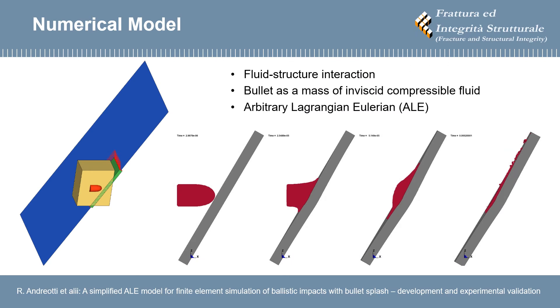The simplified model consists in treating the bullet splash as a fluid-structure interaction, where the impactor is assumed to have negligible tensile properties so that it can be represented as a mass of inviscid compressible fluid. The interaction between impactor and target is obtained by means of an arbitrary Lagrangian-Eulerian formulation, which guarantees great stability of the calculation even with large deformation fields.